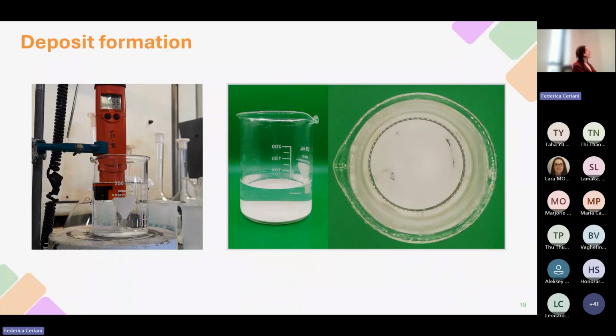In order to understand the different morphologies that are obtained, it is useful to look at what occurs within the sealing bath during the pH adjustment. The pH adjustment is performed simply by the addition of a few drops of a sodium hydroxide concentrated solution. And by looking at the video, we could note that as soon as some drops of this solution are added to the sealing bath, some whitish precipitates are produced. And at the end of the pH adjustment procedure, when the stirring is stopped, a white precipitate and deposit is observed at the bottom of the beaker.